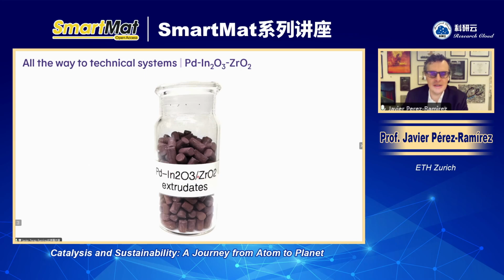In addition to indium oxide, which is the primary active phase, it's very important to have the right carrier, and in this case it is monoclinic zirconia. And you can see here that we also have palladium in the catalytic material. Palladium is essential in order to boost the activity of the catalyst by improving the splitting of hydrogen, which is actually the rate limiting step of the reaction over the indium oxide.